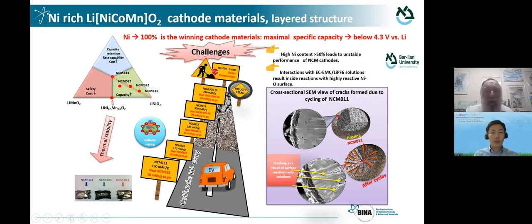What is nice about these materials is the relatively high specific capacity, but the voltage we are talking about is relatively low. We can extract all the specific capacity up to 4.3 volt, which is not too bad. This means that here we can have high specific capacity and in fact high energy density without endangering too much the anodic stability of our electrolyte solution. But what is the problem? As we go high with nickel, we also go high with problems.